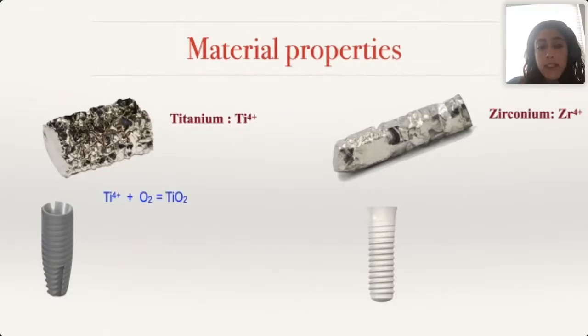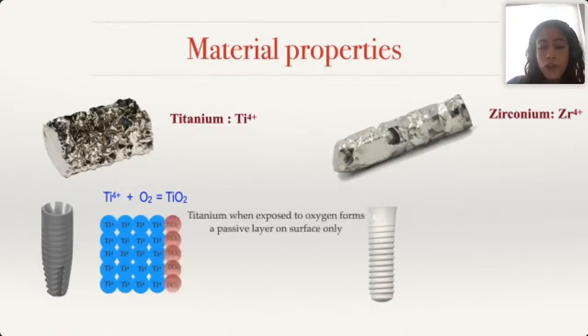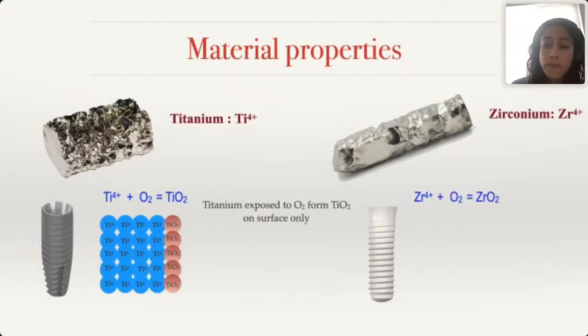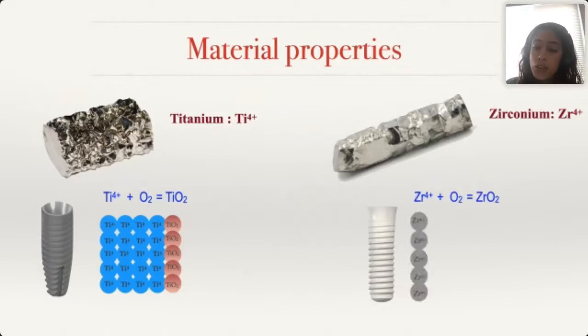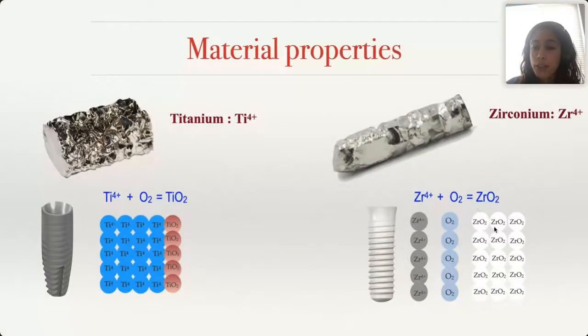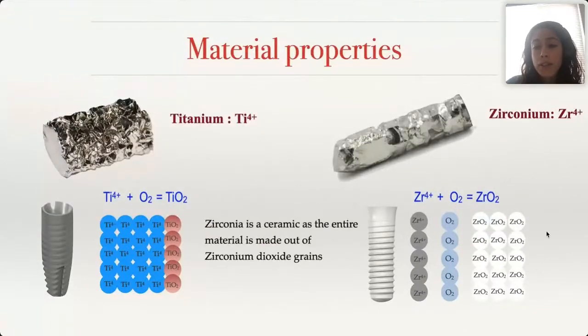Titanium, when exposed to the environment, forms an oxide surface. So it becomes titanium oxide only on the surface, but not within the core of the material. For zirconia, when it gets combined with oxygen, the entire material gets combined, so every little grain is made out of zirconium plus oxygen. That's why zirconia is considered a ceramic, because the whole material is oxidized and inert.